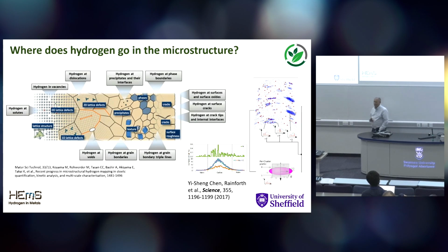Hydrogen is a very difficult subject because we can't see it. But we know roughly where it goes into the lattice. So here we have a microstructure, and it goes in all sorts of places. The hydrogen can go into vacancies within the lattice. It quite likes it there. It goes into the grain boundaries, into voids, dislocations particularly, lattice defects, precipitates, and I'll talk a bit more about those. It will go to cracks and all sorts of places. So there are lots of different places that hydrogen can end up in the structure.